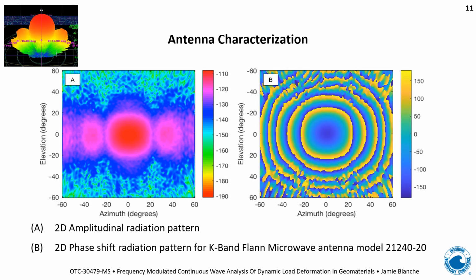And finally, to round off the equipment characterization section, it's important to understand what the footprint, essentially, of the radar signal looks like. So we characterized this in an anechoic chamber, and we now understand what the radiative pattern resembles. On the left-hand image, we're getting amplitude measurements, and on the right-hand image, we're looking at phase shifts. What we're getting out of both of these images is the dispersion characteristics of the emitted signal, which when we keep the radar antenna approximately 10 centimeters away from the sample, the red spot, for example, on the left-hand image is of the same dimensions as the sample itself.